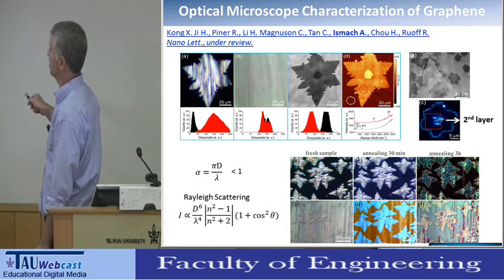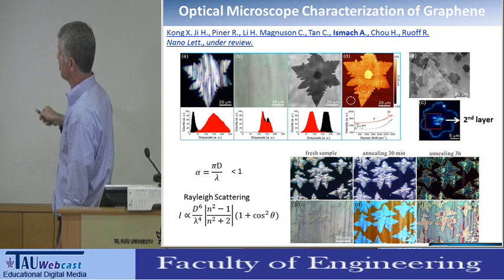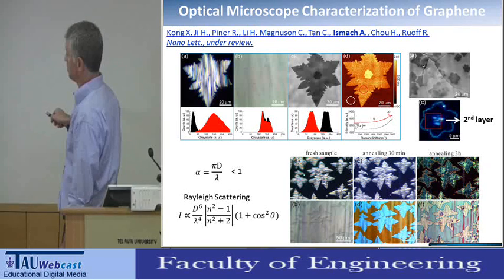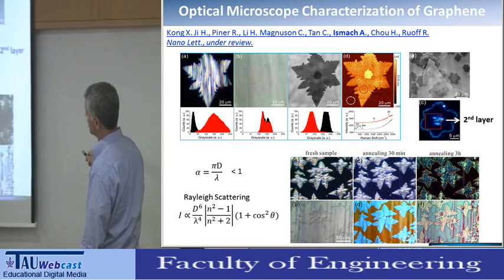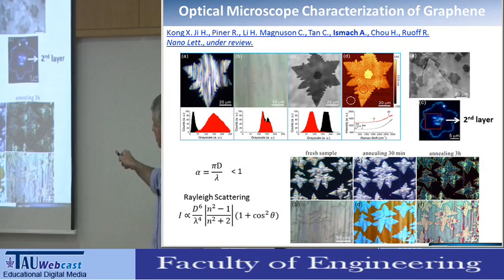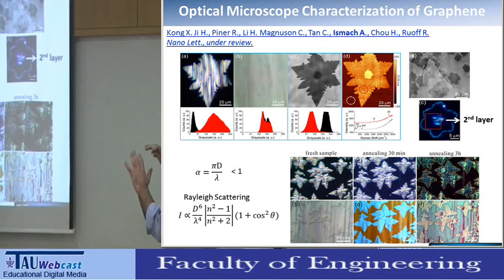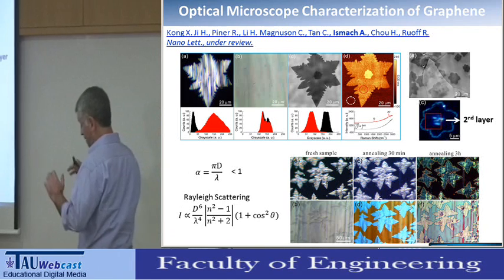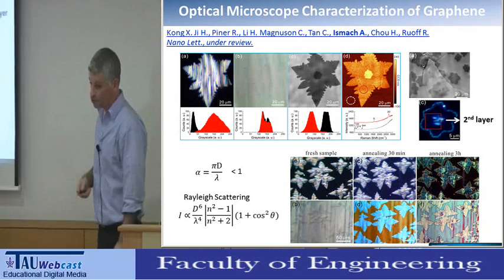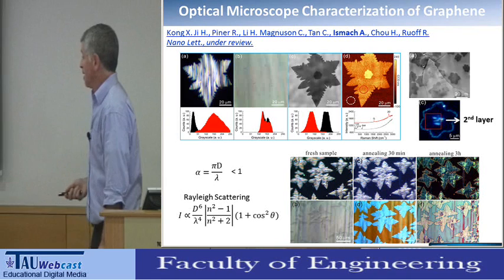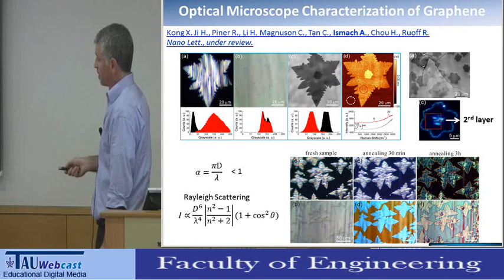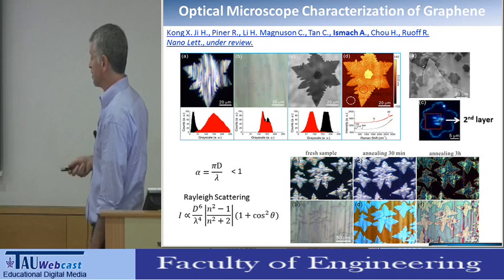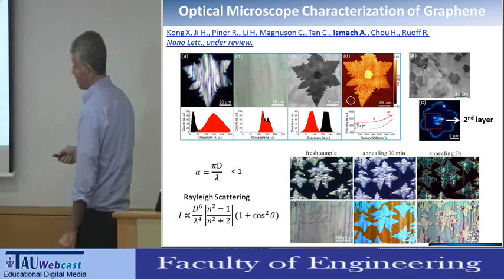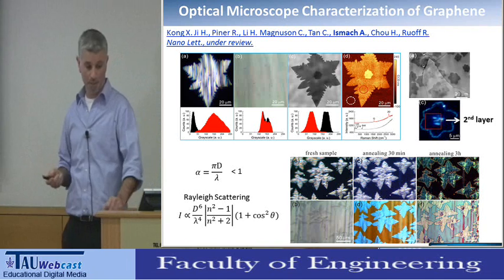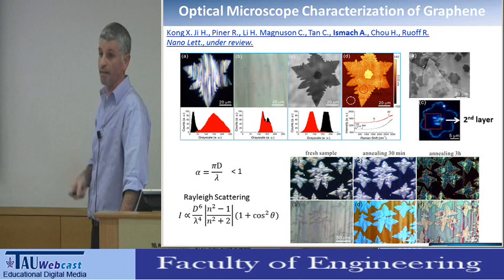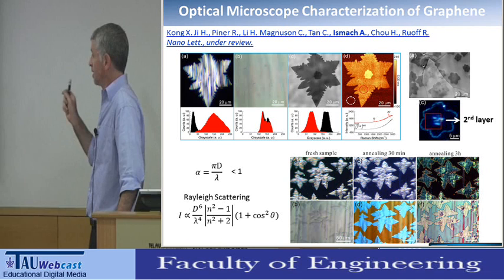This is another area of a similar sample where you can see submonolayer growth, but you cannot see the steps. But even in this case, you can see there is a topographic edge at the edge of the graphene domain. And you can show that in Rayleigh scattering, the intensity of the scattered light is proportional to the 6th power of the diameter of the particle, and that's why it's so sensitive to very small topographic features.